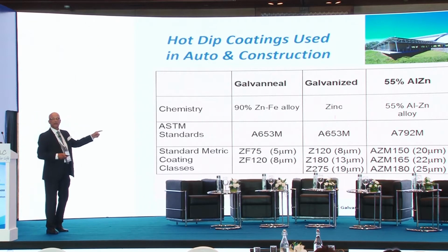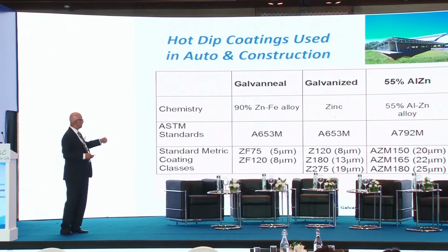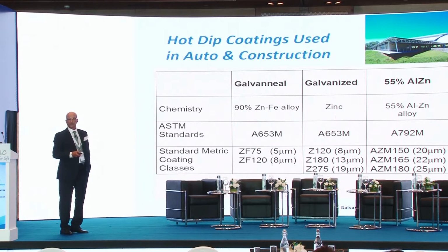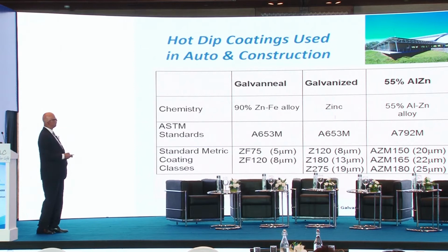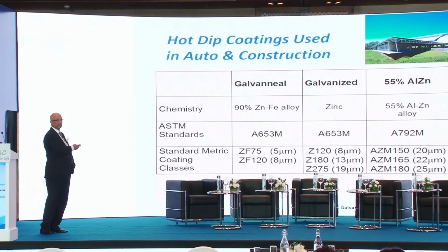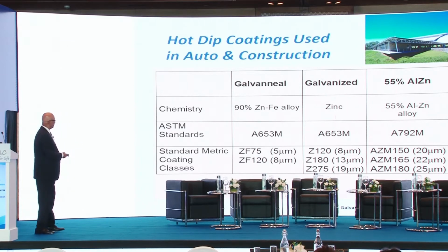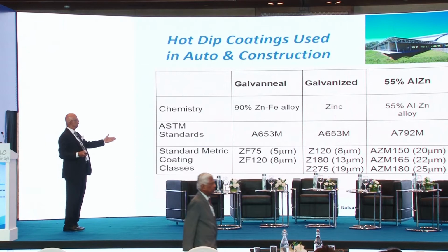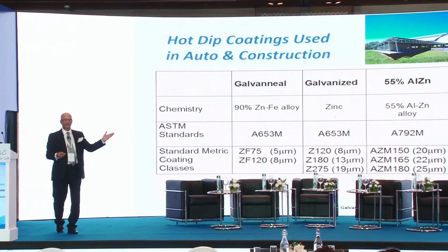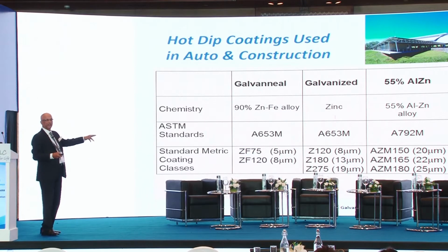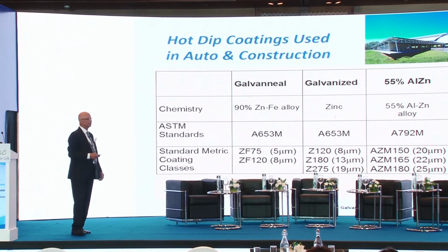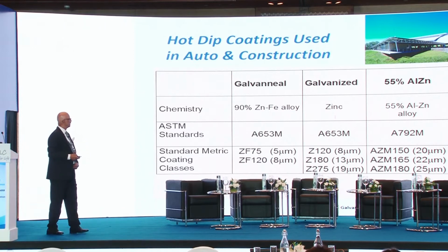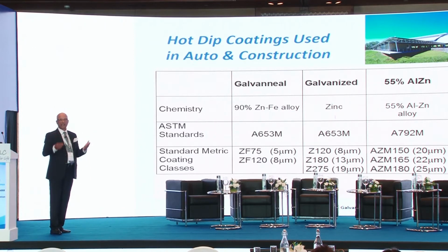Galvanized in India, the minimum amount you're allowed to use is Z120, total both sides, which means it's 4 microns per side. And then 55% aluminum zinc, the 3 typical coating weights are that. So a lot of people make comparisons between Z275 and AZ150 or AZM150, and when they look at them, Z275 is about 19 microns thick, and 55% aluminum zinc at AZ150 is 20 microns. So that's how people equate Z275 and AZ150.